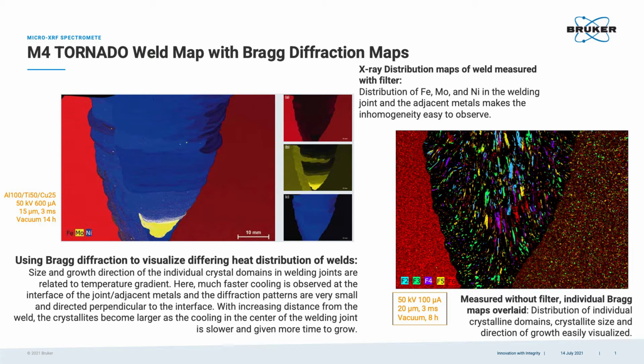But you try and do an EDS map in an SEM that rivals XRF, no chance. Speed, sample prep, everything. You just can't do it. I mean, we talked about this earlier, that people don't like the fact that you've got an interaction volume of 5 microns and that your spatial resolution isn't very good. But in terms of being able to map big things, these are real advantages. You're not getting bogged down. You're getting the average of a reasonable amount of material. It provides the extra sensitivity, provides a lot more power in terms of where you're going.